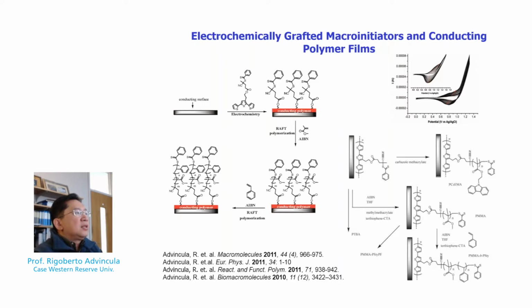So here is an example of how we have used the technique of electropolymerization to graft a RAFT initiator. RAFT stands for reversible addition-fragmentation chain transfer, on a conducting surface. So polythiophene, for example, can be electropolymerized from the terthiophene monomer with a RAFT chain transfer agent.